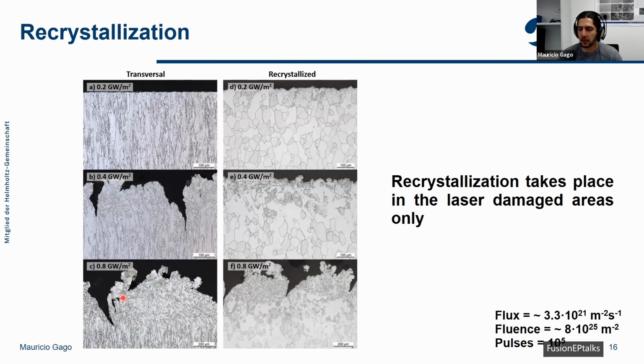And we can see that there, also because of the plastic deformation that is taking place during this expansion and contraction, there are different effects taking place, such as grain nucleation, as I said, plastic deformation, and also recrystallization. So we see a lot of smaller grains being formed in both samples, and then also some larger grains being formed, especially in the surface, even at the lower power loads.